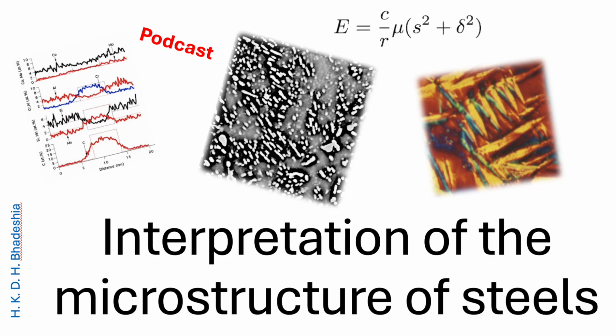And this leads to a paradox for engineering strong steels, right? The structural paradox, yes. Since the gamma boundaries aren't physically destroyed by the transformation, a structural vestige of the prior austenite grain boundary remains. It's like a ghost boundary. It is. And these boundaries are notorious sinks for detrimental impurities like phosphorus or sulfur. So that boundary becomes a weak spot. It becomes a preferential site for failure. This makes strong martensitic steels highly susceptible to impurity embrittlement. They can fail with minimal energy absorption. The structure preserves the weakness of its prior self.